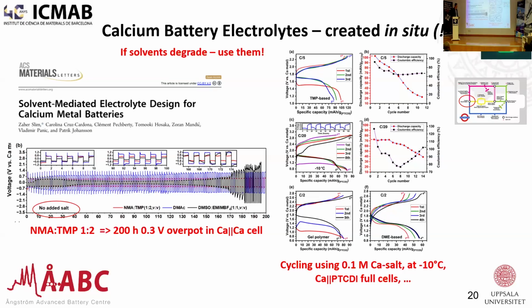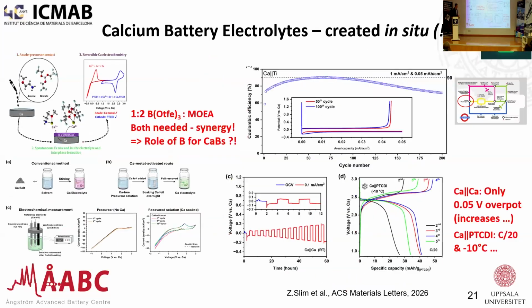So what we're doing here is actually basically that we're just making a solvent mixture, and then we're having it inside a cell, which is a calcium-calcium cell. And you see that you can actually cycle it. So there's no ions in the electrolyte initially, and that is the thing. That initially, so you have some reaction now between the solvent and the calcium surface, which then brings ions into the system. So to explain that a little bit better is actually this one, where we see that we're basically having, conventionally, we take a calcium salt and a solvent, and you make an electrolyte. Here you basically have what we call a precursor solution, and then you soak it in calcium foil, and you create a calcium electrolyte. And we can monitor that process.